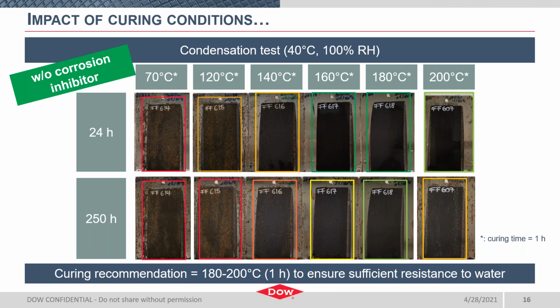Both rows show cure temperature increasing as you move from left to right. Critical to note is that none of these formulations had a corrosion inhibitor. We fully expect this to be part of a competitive advantage when formulating a paint, but we really wanted to understand how the 8016 performed on its own. And the results are showing that hydrophobicity is significantly impacted by curing temperature, or the degree of cure.